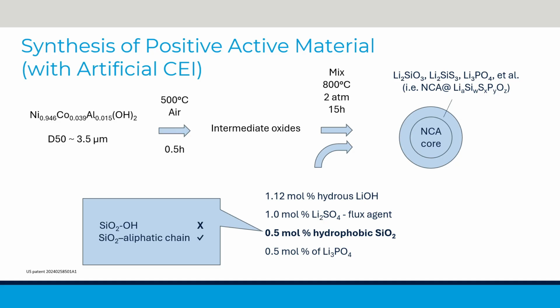The hypothesis is that, first, hydrophobic silica has better dispersion during application. It reduces unwanted agglomeration. Second, the alkyl chain decomposes during heating, leaving behind pores or channels to accommodate other species. It could maintain good electrolyte permeability and allow for lithium-ion transport while protecting the NCA surface.